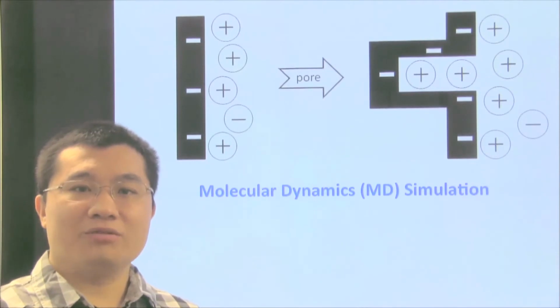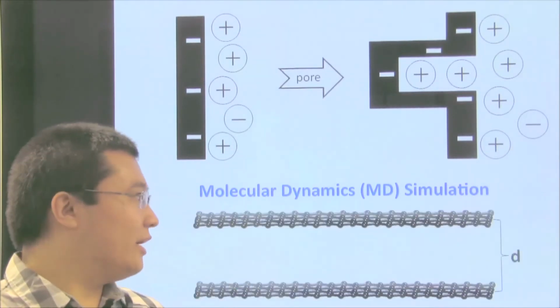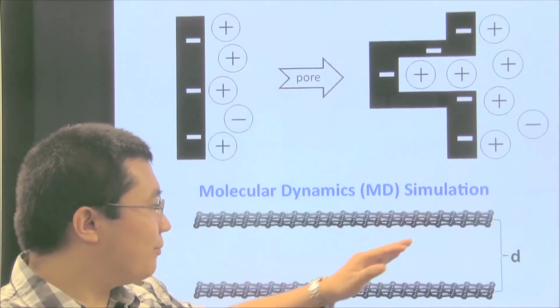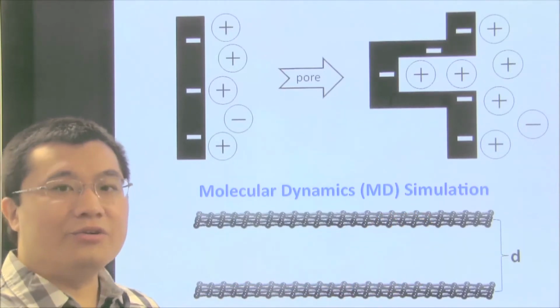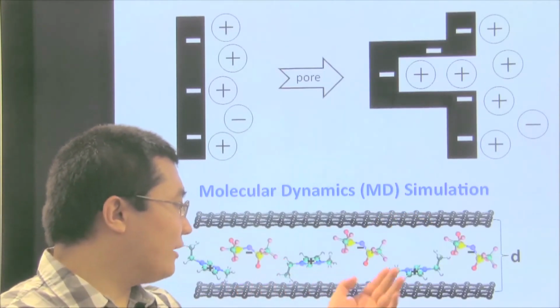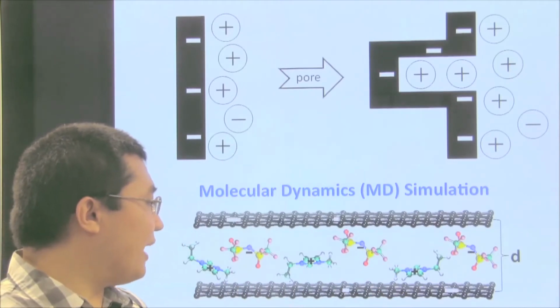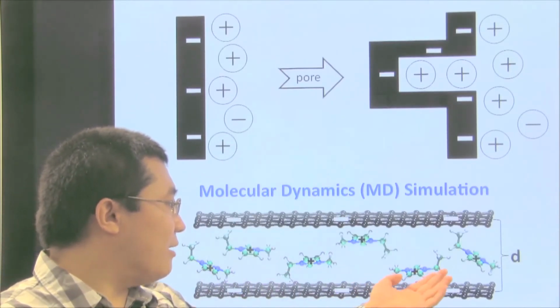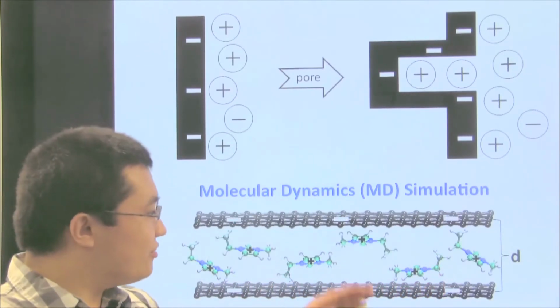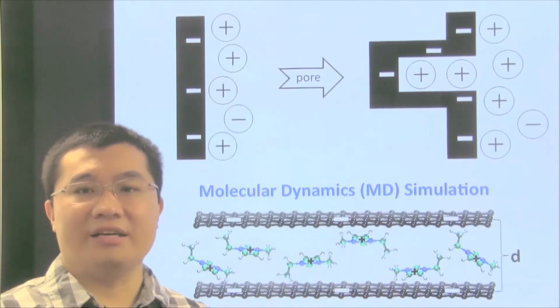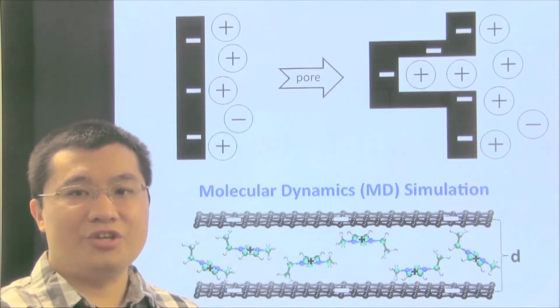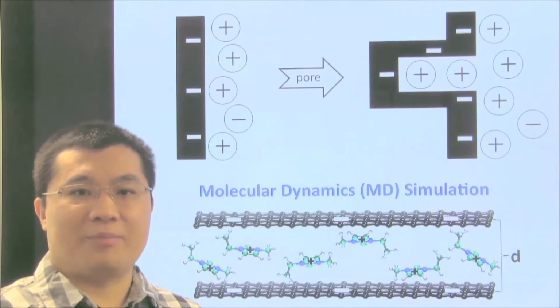For example, we modeled the pore in a carbon electrode as a slit formed by two planar graphene sheets. We used the ionic liquid as an electrolyte. When a potential was applied, more counter-ions can move inside the slit. Using this simulation setup, we studied how the pore size D influences the capacitance.